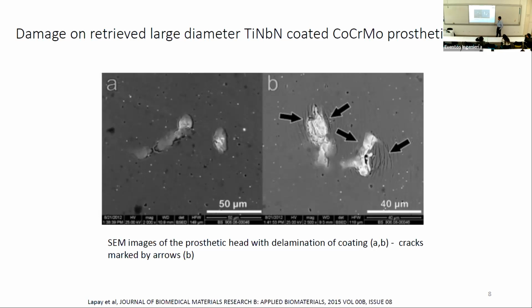So the coating was probably failing by a phenomenon called the thin ice effect. The thin layer was not being well supported by the substrate, and during contact, the stresses were high enough that the substrate underneath the coating deflects, and the coating then cracks. And this was resulting in weakening of the interface and basically the delamination of the coating.